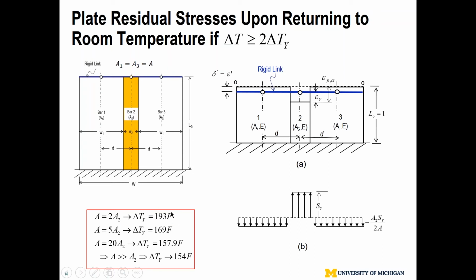I get inquiries all the time: when someone does a residual stress measurement, they get a very high residual stress beyond yield. Actually, that's not a big deal. As long as you exceed 2 times delta Ty, as long as the localized heating exceeds this value, residual stress will always be equal to or larger than the material yield strength. Obviously, if you have hardening, that will introduce higher than yield magnitude residual stresses in terms of peak value.